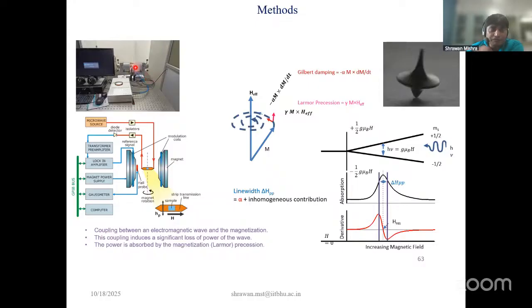So this is the device that we have in our lab. Here you can see the magnet pieces in line, and this is the RF generator. This blue cable that you are seeing goes to the waveguide that is mounted on this stage. And in the center part of the magnet, we have our sample. This can also be seen in this sketch. Here you have this blue stripe mounted on this yellow waveguide. The blue one is the sample, and the yellow one is the waveguide. Here you have a microwave source, and the other part of the signal goes to the reference, and then you can amplify this waveguide signal and compare it with the Gauss meter, and you can get a curve like this one. That's called the FMR spectra that you must have heard of, the ferromagnetic resonance spectra.